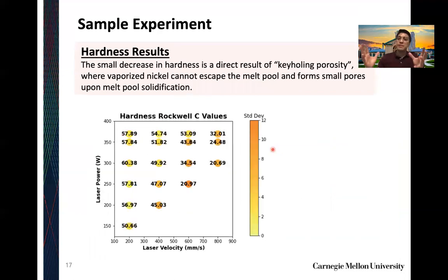Now, if we take our hardness measurements and project them on a different space, in this case laser power on the y-axis and laser velocity on the x-axis, and I'm also showing the standard deviation in our measurements through this color bar, we start to see that as you increase the laser energy density, you increase your hardness. That makes sense because by increasing the laser energy density, we are inducing more heating, which guarantees that we are melting and resolidifying all the nickel present in the material system. Now, as I just mentioned, as you increase the laser power, you increase your hardness,